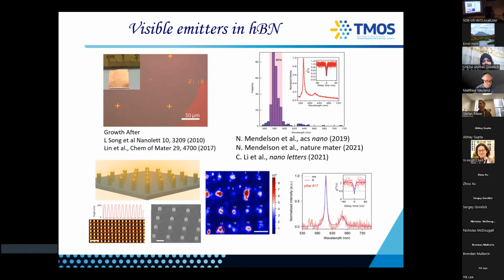So we have a lot of emitters, and most of them emit at 600 nanometers, and most of them have this signature of anti-bunching. You can also localize them by growing on pillars. This is on silicon oxide. So after a few years and following a few established recipes, you can grow HBN on anything you like, and you will get single photon sources. Now, at room temperature, they don't mean anything. So how do they behave at low temperature?